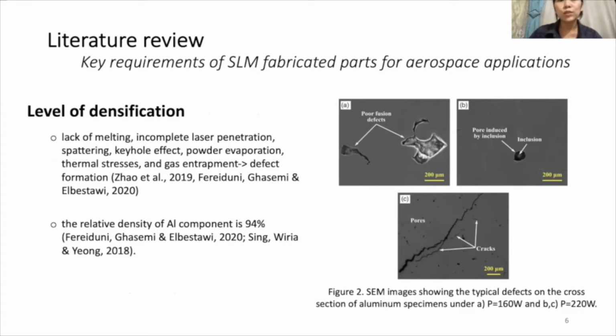First is the level of densification level. The densification level is a characteristic that directly affects mechanical properties of printed parts. Regarding the layering nature of additive manufacturing technologies, it gives both advantages and disadvantages. There are many risks that can be caused by SLM nature, such as lack of melting, incomplete laser penetration, spattering, keyhole effects, powder evaporation, thermal stresses, and gas entrapment. These limitations are the main causes of defect formation. All of these issues could result in porosities and cracks, and can adversely influence the densification level.